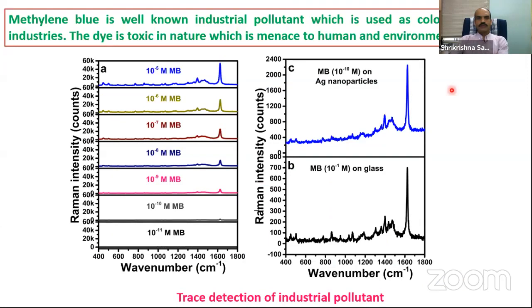Once you have optimized this, I can measure now this. Methylene blue is a very toxic dye, which if present in the water, is not good for our health. So I have to have some technique which will be able to detect very low concentrations of methylene blue. You can see that if I have 10 to minus 10 molar of methylene blue, and this is 10 to minus 1 molar of methylene blue, if I put that on glass, I will get the intensity of around 600 to 700.